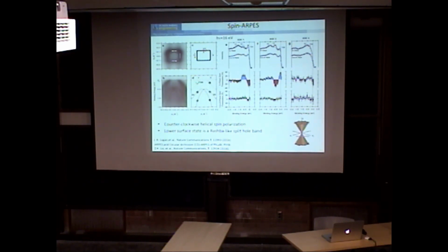So that's saying that this surface state is going in this direction. The arrow is going, we're looking at the point of the arrow. Here we're looking at the tail of the arrow, the opposite directions. If I look at this point, this blue one, this is point 2 here, you'll see it's blue-red. So this corresponds now to a spin that's going helically around here. If you look at this point here, we're not sensitive to any spins in this direction, and you should see nothing. So this, we believe, is the first direct demonstration that this is a topological material. And we see that surface state.